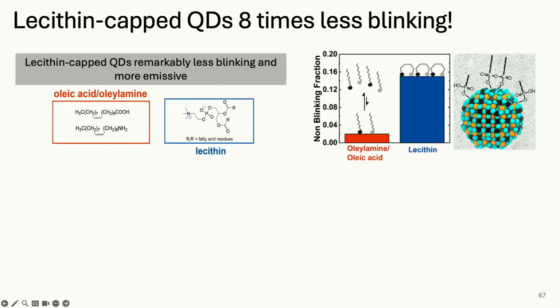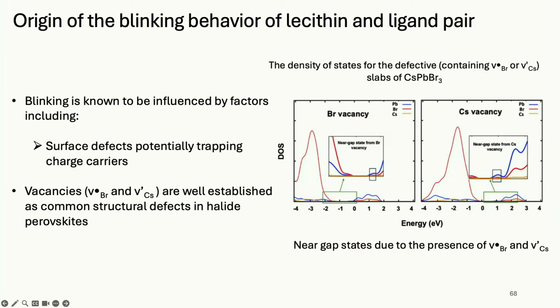Okay, so this is a histogram of how many of them are non-blinking at any given time. And the lecithin shows that almost 20% of them are not blinking. Whereas if you have these capping ligands, oleylamine and oleic acid, then you only get like 2% non-blinking. Okay, and so here you can see we have like carboxylic acid, and here we have an amine. And so these become sort of like a carboxylate and an ammonium, so a negative and a positive. But instead, the lecithin has the negative and the positive on the same molecule. So the main difference is whether you have two ligands, each of which has one charge, and one ligand that is both. And so I'll come to the main reason we think there's a difference here.